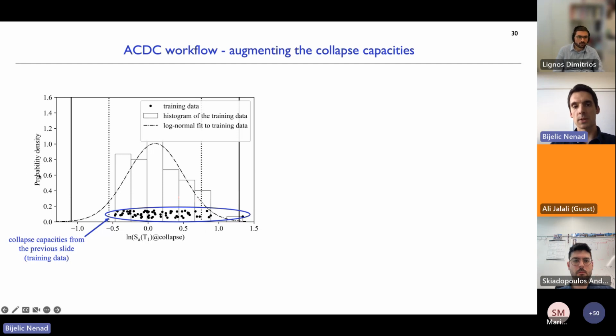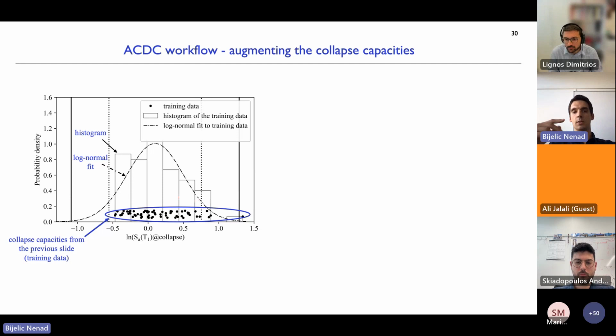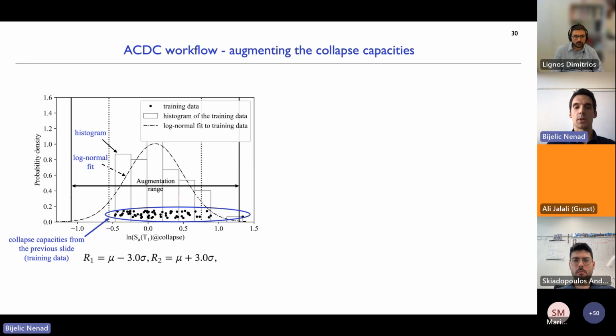Where the probability density comes in is in these histograms that represent the data, and then the log normal distribution fitted to the data. So you take the data, you fit a log normal to it. And so the question now is, where should I augment the data? Where should I add this data? This is what we call the augmentation range. One way to do it is to augment in the range within plus and minus 3 standard deviations from the fitted log normal, because that's where you would expect to have 99% of your data if you trust this log normal distribution.